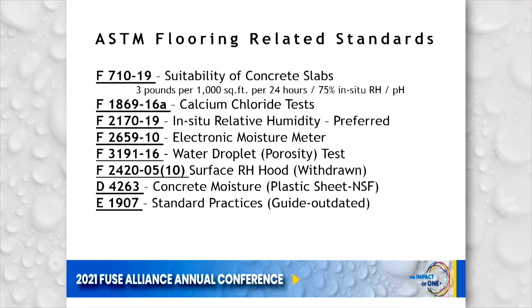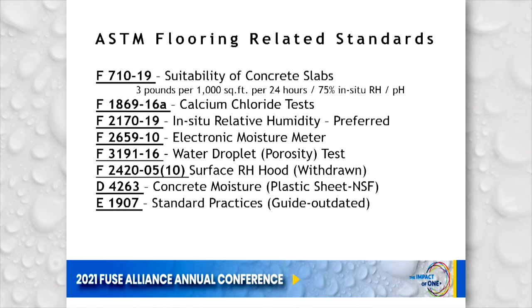I've used the word preferred after that test method because today it is. Years ago, we relied on calcium chloride. Pretty much every floor covering, adhesive, and coating manufacturer is listing the in situ test as either preferred or, in fact, the required test. But there should be an awareness that if you're going to use an electronic moisture meter, there is a standard practice for doing that, ASTM F2659. F3191 is now a water droplet test where we're going to look at the porosity of that concrete, decide whether we should consider it porous or non-porous.